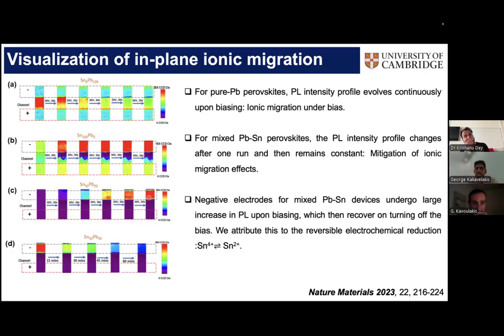So yeah, therefore definitely, there can be some electrochemical reaction that can happen on the electrode because it's directly touching the perovskite. For the lead-based case, at least here, our electrodes were chromium and chrome gold, so these are known to be much more stable chemically. That's why we use chrome gold. Chrome gold is known to be a more stable, chemically inert electrode as compared to others like aluminum or silver. So in that sense, chemically, we didn't really see any significant reaction, but of course, electrochemically, it can still happen. Okay, thank you.